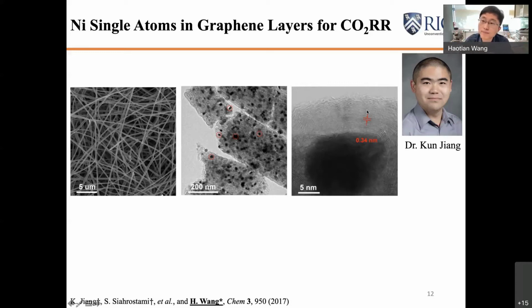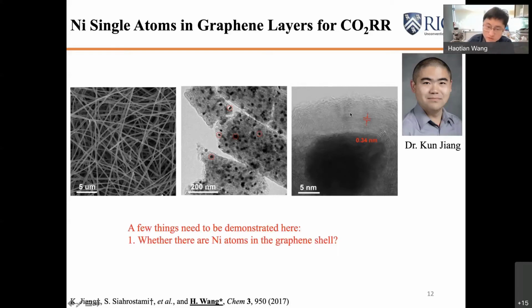And also during the synthetic process of the graphene, if we intentionally introduce some defects, we might be able to trap a lot of nickel atoms in the graphene shell regions where the reactions can happen. So then we ask ourselves several questions.